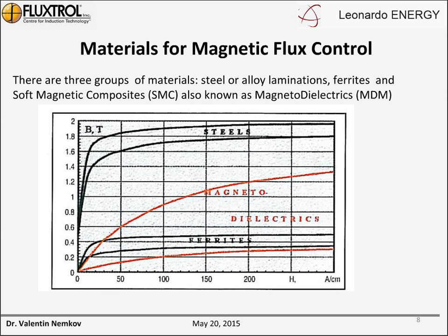The ferrites have the same behavior as steels, but with much, much lower values, four times lower saturation flux density. And in weak field, permeability of ferrites is very high, but then it drops very quickly when material saturates. And finally, red areas show you a wide range of properties of magnetodielectrics, which combine the ferrite area at high saturations and approach the steel, the upper curve, for low-frequency magnetodielectric.